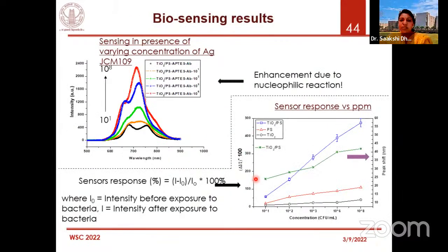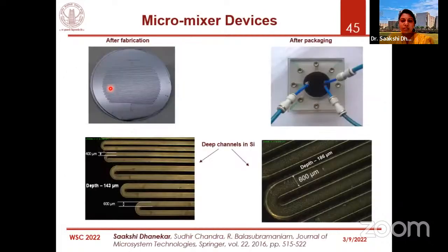So this is one thing that we saw, that as the concentration was increased, we could see enhancement in PL, which is in a way better in comparison to where the photoluminescence gets quenched, right? Because there is a limit there. Here there was really no limit. We could go from higher concentrations to lower concentrations. So this is also published in case anybody wants to read it in more detail.